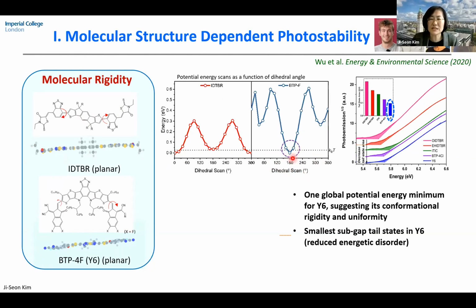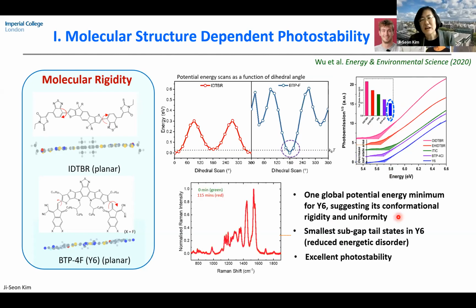This conformational rigidity and uniformity will induce conformational order, therefore reducing the energetic disorder. It can be seen in the experimental data when you measure the subgap trap states, with Y6 showing the lowest subgap trap state, indicating this rigid-structure-induced decrease in energetic disorder. And when you make this planar and rigid molecular structure, surprisingly, the molecules are really stable under photoexcitation.